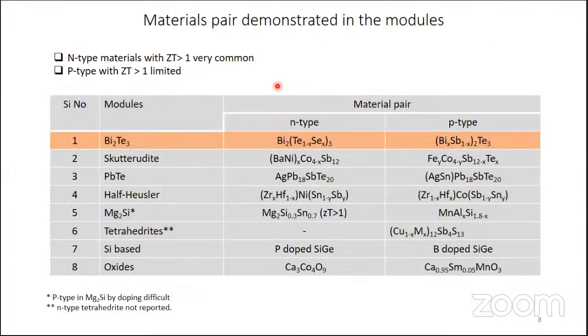So these are some of the commercially produced and reported thermoelectric modules and the material pairs used. And of course, bismuth telluride is very popular. Anybody can get it online also. A lot of products are available. But other than that, some companies tried skutterudite, cobalt antimonide based material, and then lead telluride, half Heusler, Mg2Si. There are a lot of such products, but commercially getting them is difficult.